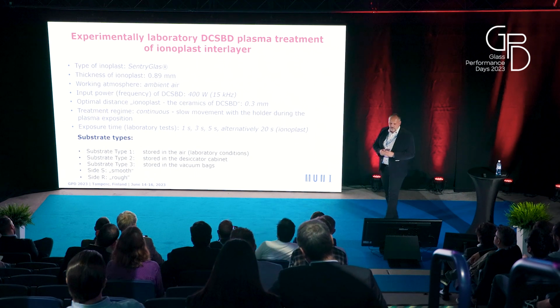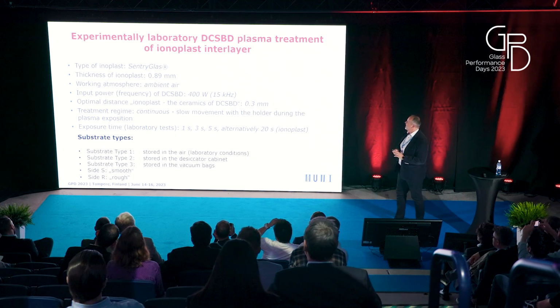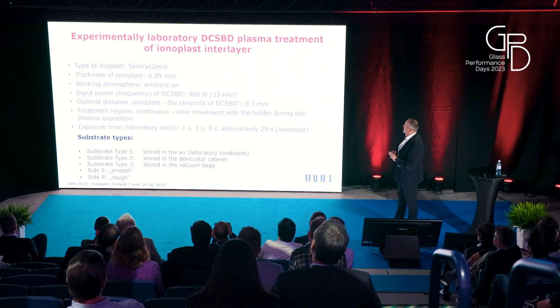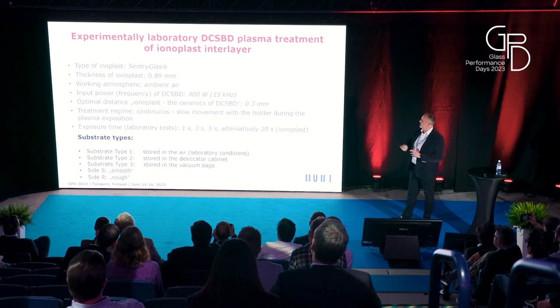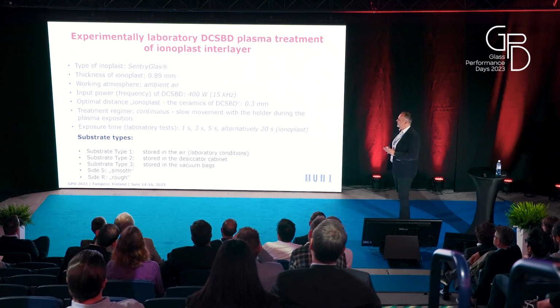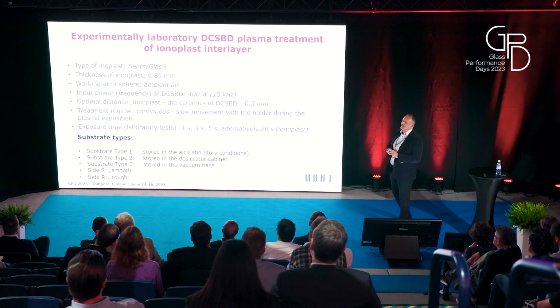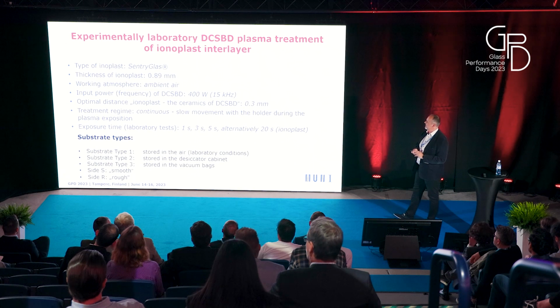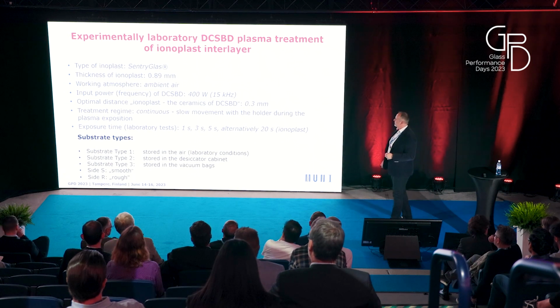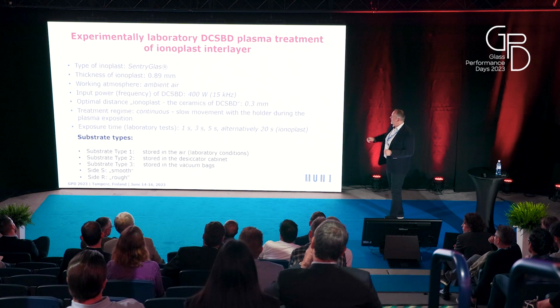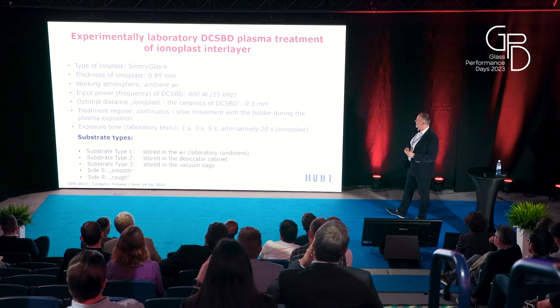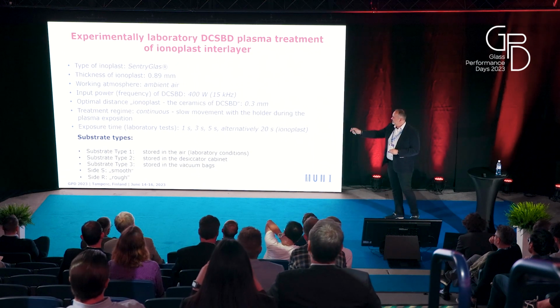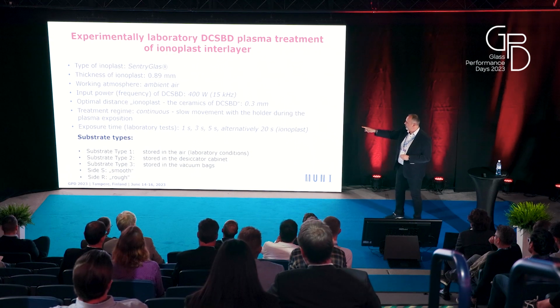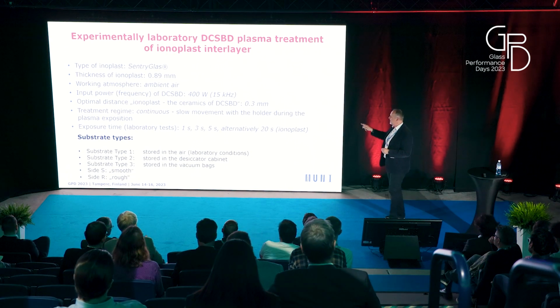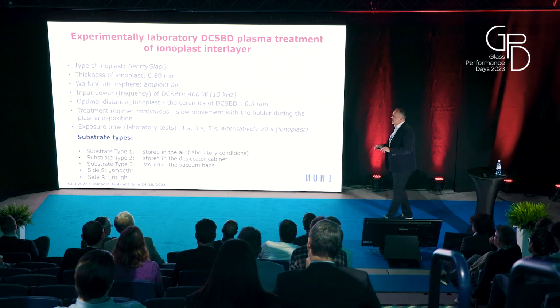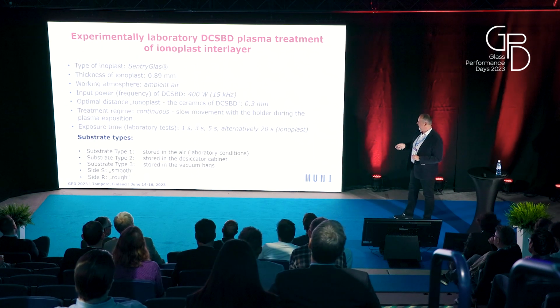Experimentally, in our laboratory, we investigated the plasma treatment of ionoplast. As the interlayer, we used SentryGlas with a thickness of 0.89 millimeters. As a working gas, we used ambient air. Input power was 400 watts. We kept the sample at a distance of 0.3 millimeters, and exposure times, as you can see, were really very short, from 1 second to 5 seconds. And alternatively, when we wanted to study overexposure, we used 20 seconds.